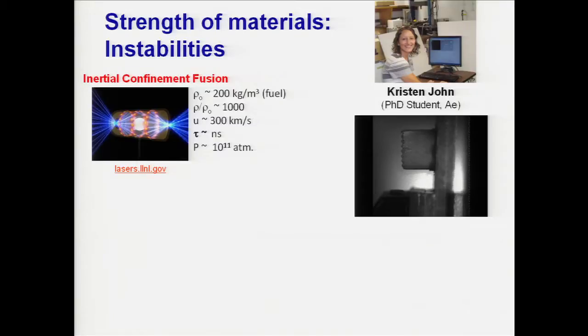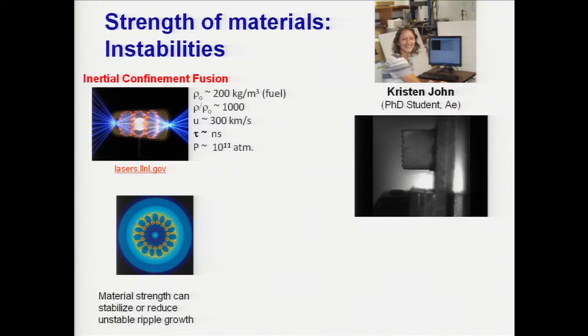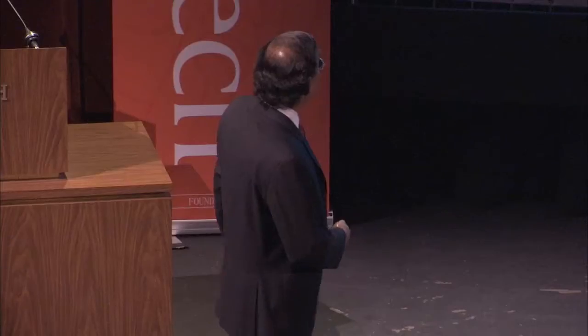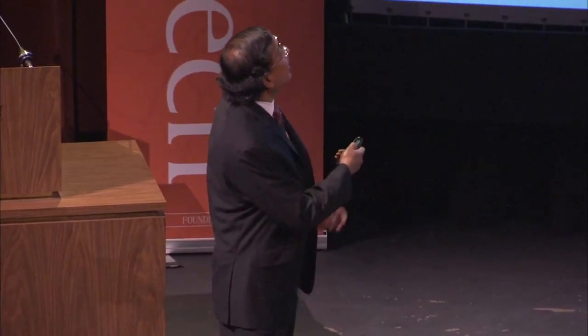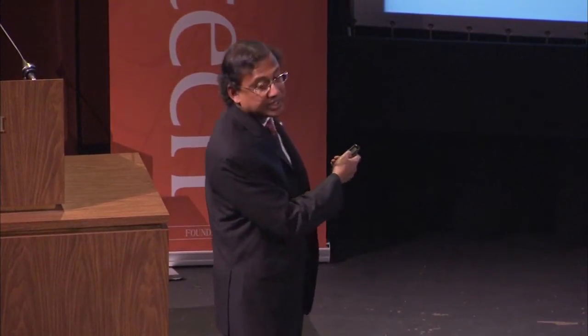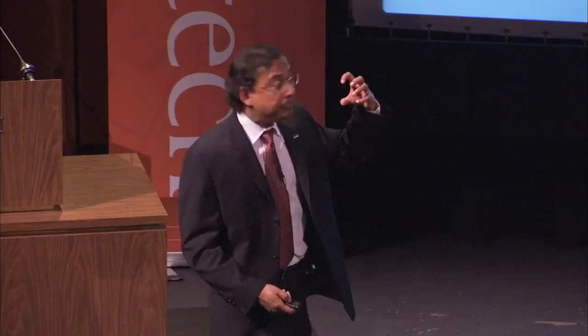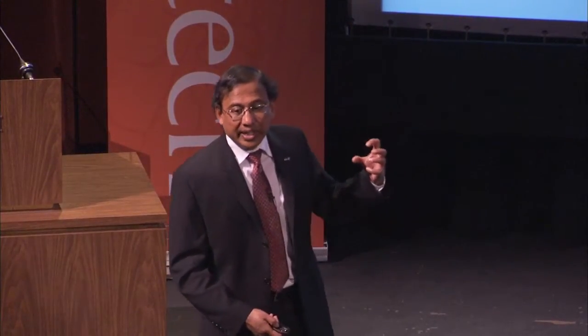But when you do that, not everything happens perfectly. If it implodes symmetrically, then you can create this very, very high pressure. But what happens is that you develop instabilities, you develop spikes, and these spikes don't allow the pressure to reach the very high pressures at the core of the sun. Then you can't have fusion. So one of the ideas is that if you increase the strength of the capsule, then somehow you can suppress these instabilities. But when you are compressing it so fast, the equivalent impact velocity is about 300 kilometers per second. At such very high speeds, you want to know the strength of the material, so you have to have the ability to measure the strength of the material at this very high pressure.